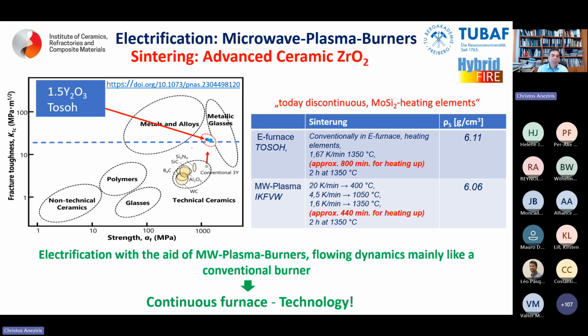Normally, it's sintered discontinuously in a chamber kiln where molybdenum disilicide heating elements are used. And we have compared normal conventional heating using heating elements as well as the microwave plasma. And we have seen that we have decreased the heating up time by approximately 50%. And this would be perhaps very interesting if we go away from today's discontinuous approach to a continuous one. So, electrification with the aid of microwave plasma burners, we have fluid dynamics mainly like the conventional burner.